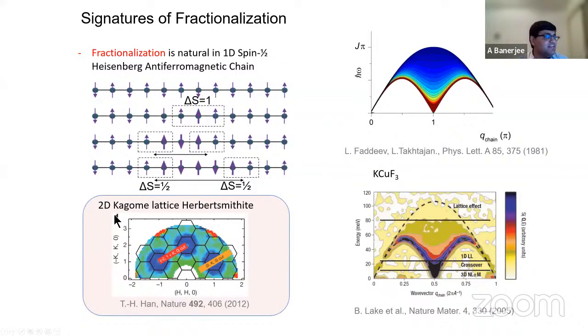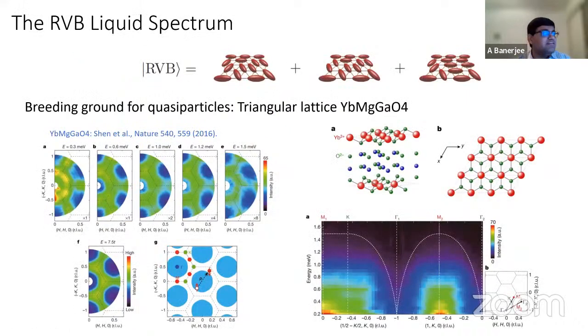And that's exactly the signature that we are looking for in quantum spin liquids, as was shown in this Nature paper by the MIT group. And in resonant valence bond systems like this triangular lattice antiferromagnet, ytterbium magnesium gallium oxide, people have shown that you can see this kind of large, broad, blobby states in both energy and momentum, which is actually one of the signatures of a quantum spin liquid, or spin liquid, quantum or not, as we mentioned.